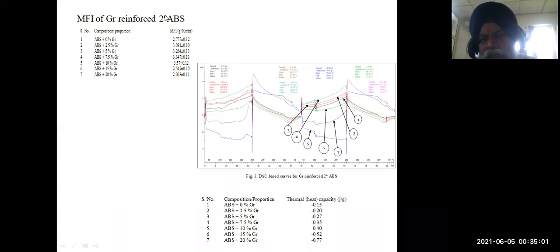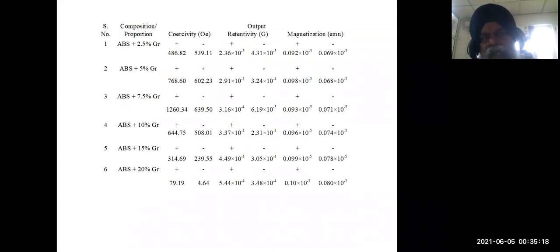You can see in this typical DSC curve, with the reinforcement of graphene, like in ABS I am putting, as the graphene reinforcement is increasing, the energy capacity in joule per unit gram is increasing. That means this is going to be more thermally stable. So we also try to correlate with the magnetic property, how much will be the coercivity, how much will be the retentivity, because I am interested to use this as some sensor which can be actuated with the magnetic field, right?